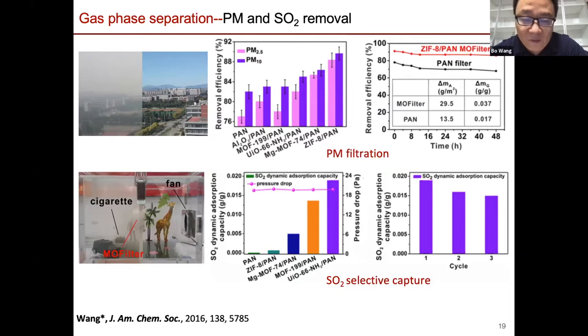What we observed, especially for some of those MOF nanoparticles, is that when you make them small enough, you are facing a lot of static. I think we all experience such a thing. When you make it small enough, you're experiencing the static electric effect. But when you are covering the surface of substrates using nano MOF particles, this phenomenon is even more pronounced. So we can utilize this to actually capture the aerosol and attach it onto the surface of our membrane. At the same time, since MOF pores can naturally uptake some of those pollutants from air, for example, SOx and NOx, eventually you can have such a membrane filter out PM2.5, PM10, and at the same time absorb some of those SOx and NOx into the membrane to clean out some low concentration toxic condition.